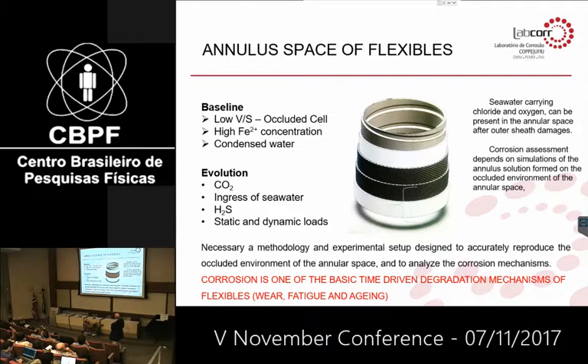And together with condensed water, you can have CO2. And CO2 will drive different corrosion mechanisms, but basically CO2 corrosion, with the difference of the high iron concentration. And at the same time, from the external sheet, you can have the ingress of seawater, H2S, and static and dynamic load. So it makes it much more complicated to assess the possible corrosion mechanisms in the annular environment.